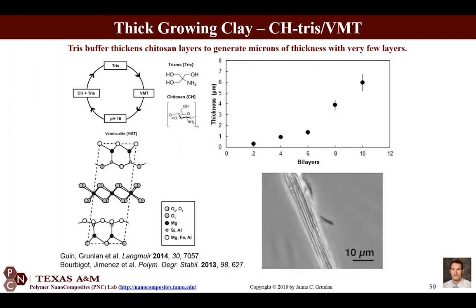Many people, though, say, well, 10 bilayers, that's 20 layers, that's a lot. And so there's a number of things we've done to reduce the number of layers we need for high barrier. We found from another group that they had added this tris buffer. And when they added that with the cationic polymer, they got a thicker growth with clay. And it was because there's some kind of complexation between the tris buffer and the clay in solution.